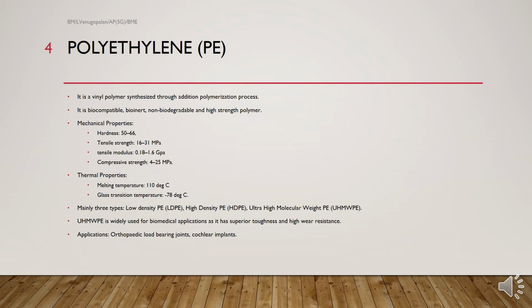The next one is polyethylene. It is a vinyl polymer that is synthesized through the addition polymerization process. It is biocompatible, bioinert, non-biodegradable, and a high strength polymer. It's got very good strength. As for its mechanical properties, it has a hardness of 50 to 66, tensile strength between 16 and 31 megapascals, lesser than PMMA, but still quite strong. Tensile modulus is 0.18 to 1.6 gigapascals, and compressive strength is 4 to 25 megapascals. The thermal properties are a melting temperature of 110 degrees centigrade, and a glass transition temperature of minus 78 degrees centigrade.